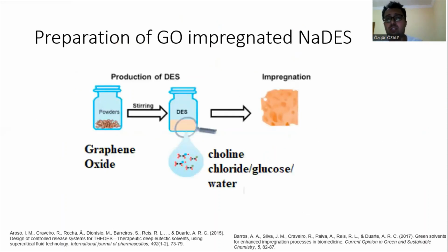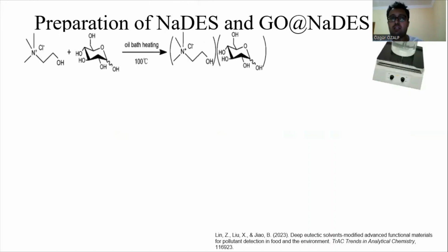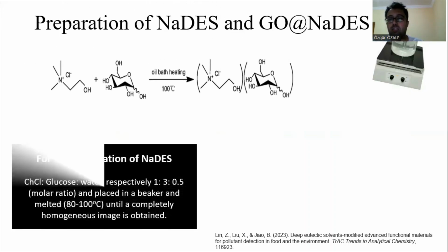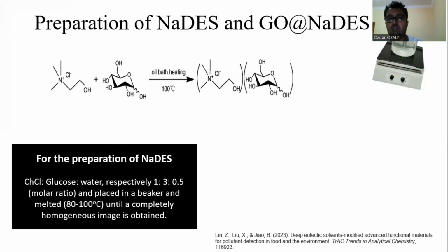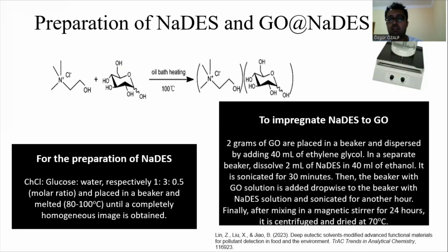Preparation of graphene oxide impregnated with natural deep eutectic solvents. You can see graphene oxide made by Hummers' method. Choline chloride and glucose are simply added in a beaker and heated to approximately 100 degrees centigrade, and after combining you can observe the natural deep eutectic solvent. We use only 2 grams of graphene oxide and add ethylene glycol. After mixing, we add the natural deep eutectic solvents in ethanol, because solubility is very high in ethanol.